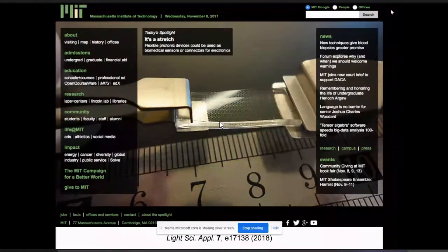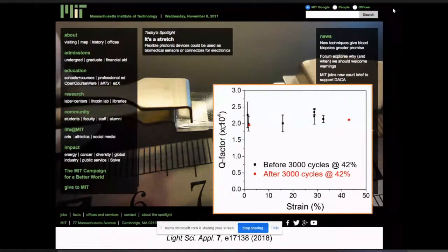By using such an architecture, we were able to create stretchable photonic devices with a very large geometric deformation capability. We can stretch to a relative elongation of over 40%. We also see that this device can sustain 3,000 repeated deformation cycles without any appreciable change of optical performance.